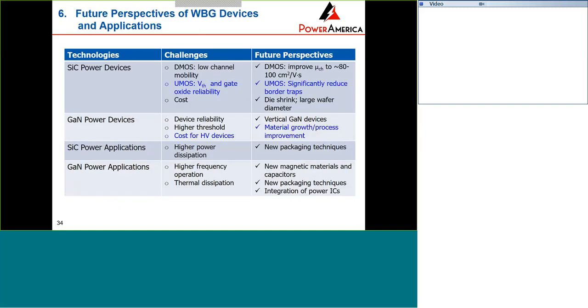So in summary, for silicon carbide power devices, again for DMOSFET, we need to improve the channel mobility, 80 to 100 centimeters square per Vs. For trench MOSFETs, we need to significantly reduce the border traps to reduce the hysteresis in the transfer curve. And also for both devices, we need to reduce the cost by large wafer diameters and die shrinking, low material